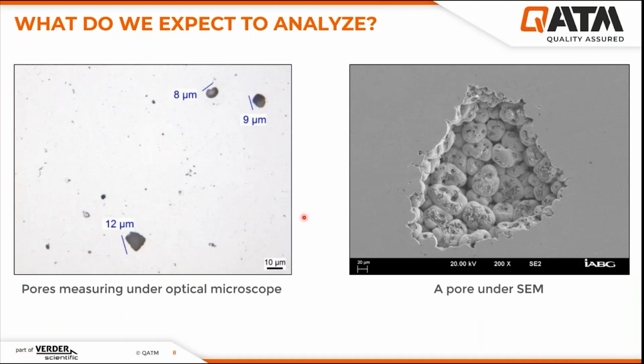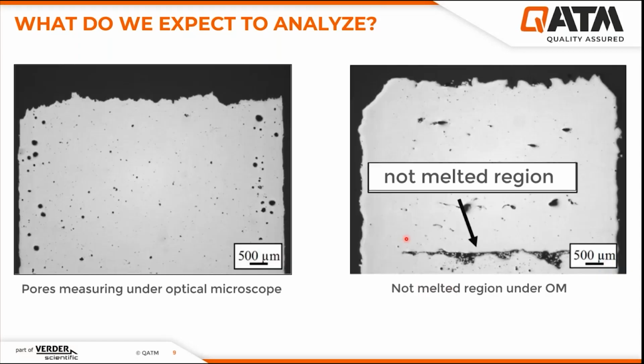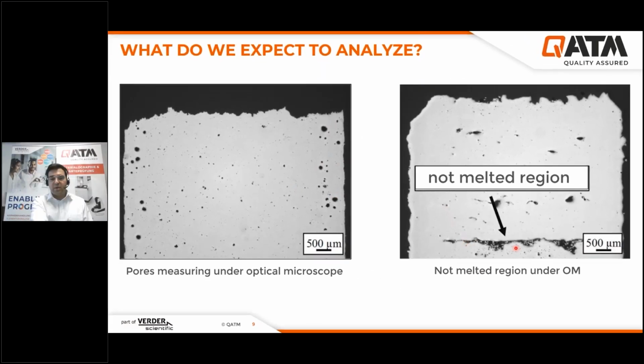What do we expect to analyze? Here are some images from literature, and you can also find the references later in the presentation file. On the left-hand side, we can see the pore measured under an optical microscope, and on the right-hand side is a pore under a scanning electron microscope. You can also see the pores under an optical microscope, and some other defects we can meet here, such as not-melted regions.